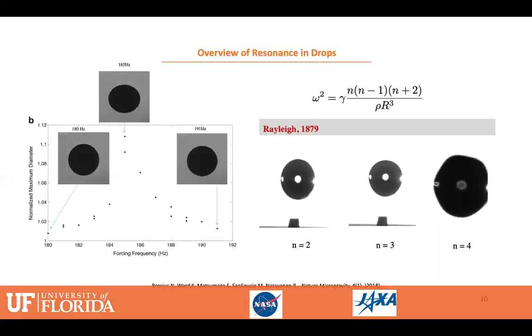You can also have larger radii of drops in space, which is somewhat difficult on ground because large radius spheres tend to sag and you really don't get a sphere at all. So an advantage to go to space is that you can use different ambient fluids such as nitrogen and argon. A second advantage is that you can use larger radius drops and go through a sweep of frequencies.